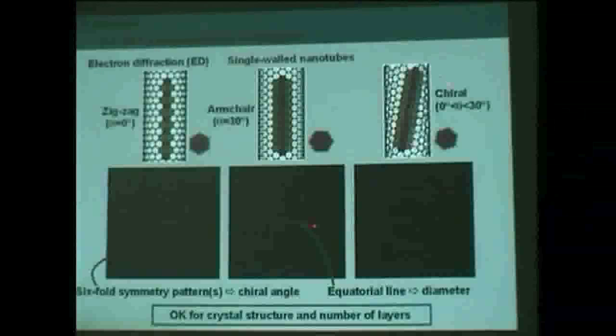Now we take a more complex case, which is chiral. In this case, there is a difference of orientation between the top layer and the bottom layer. They are misoriented. As a consequence, what we get is the sum of the two patterns.